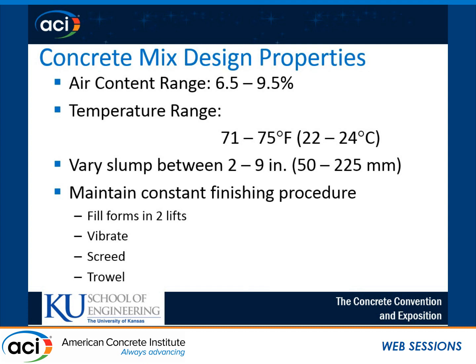And this is getting into probably the most important part for maintaining control and getting good data out of this. When we do a series, it's best to use a single operator for placing, finishing, curing, and doing the subsequent evaluation of each of these mixes. The procedure we use is we fill our forms in 2 lifts, vibrating between each one. We follow that with a plywood screed and then a hand float.